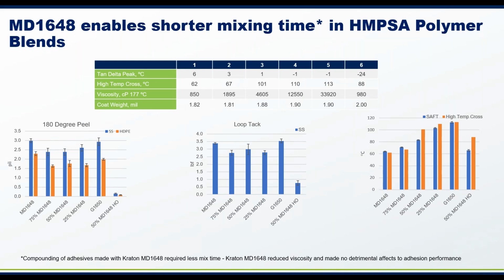Here we show the viscosity range of the 6 formulations from the previous slide, and you can see the formulation 1, which has the highest loading of the MD1648, offers the lowest viscosity. In addition, compounding of adhesive made with 1648 also requires less mix time, while making no detrimental effects to the adhesion performance. And therefore, MD1648 provides the flexibility for adhesive manufacturers to tailor their formulations that are suitable for their needs.